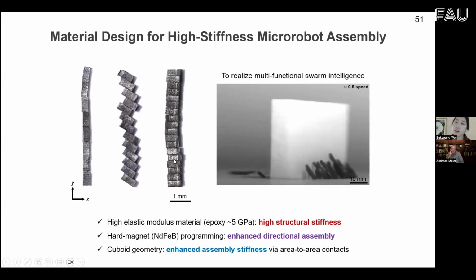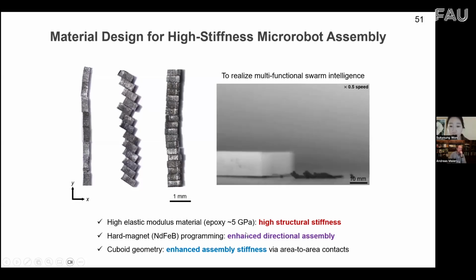Because the low stiffness of the microrobot assembly can be easily disassembled, it could not achieve this kind of complex task. So we chose the high elastic modulus material, epoxy, for high structural stiffness. The epoxy polymer has a high cross-linking density and high glass transition temperature, so it results in this high mechanical property with a Young's modulus of 5 gigapascals.